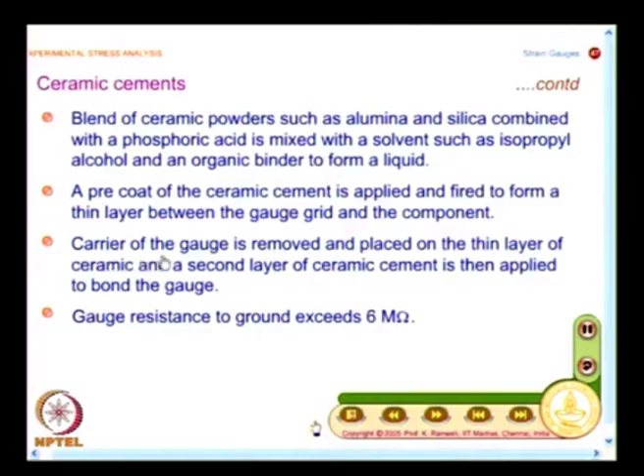So, you have an initial layer of ceramic on the specimen. Your normal carrier of the gauge will not withstand such high temperature. So, the carrier of the gauge needs to be removed, and you put a second layer of ceramic cement to bond the gauge. And when you do something like this, gauge resistance to ground will be only about 6 megohms. It is much smaller, but that is the best that you could get when you use these kind of ceramic cements.